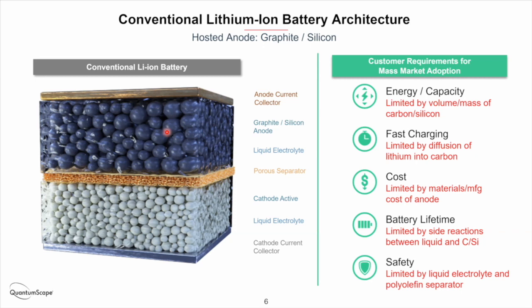And then also in the formation cycle, what's called the formation process, what you're forming predominantly is the anode SEI, the solid electrolyte interface that forms on the surface of the graphite particles. And this formation and aging process is one of the most cost intensive parts of battery manufacturing. It can take weeks to form and age the battery. These are weeks after the battery is made, when it's in its highest value state, that you have to, as a battery manufacturer, just carry as inventory on your shelves and run through cyclers to test them. So it does contribute to cost as well.